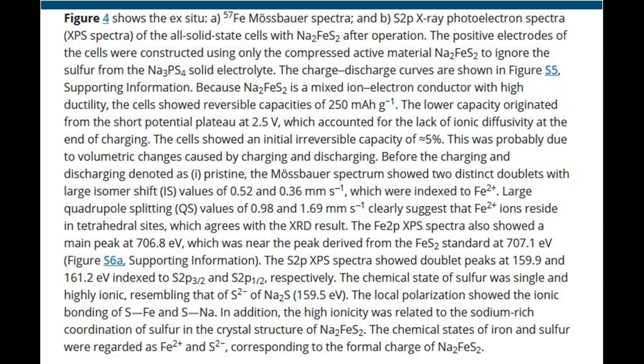Before the charging and discharging, denoted as I, pristine, the Mossbauer spectrum showed two distinct doublets with large isomer shift, IS, values of 0.52 and 0.36 mm s-1, which were indexed to Fe2+. Large quadrupole splitting, QS, values of 0.98 and 1.69 mm s-1 clearly suggest that Fe2+ ions reside in tetrahedral sites, which agrees with the XRD result.